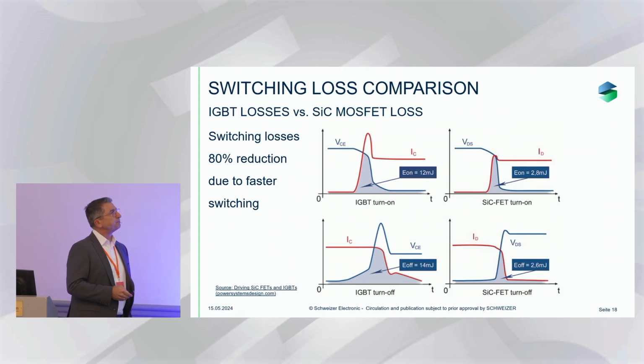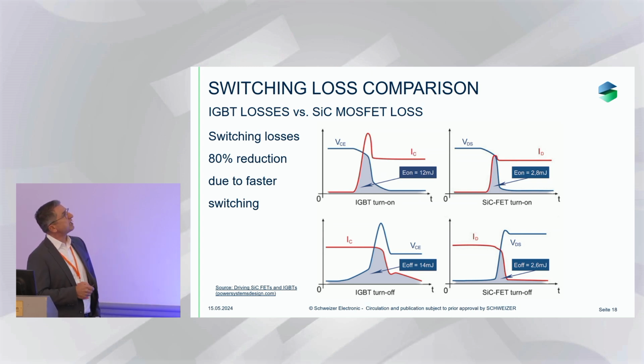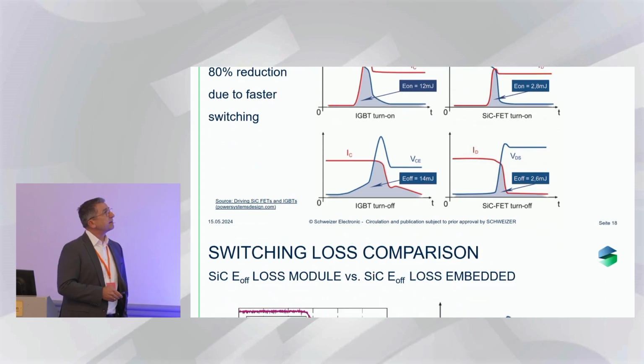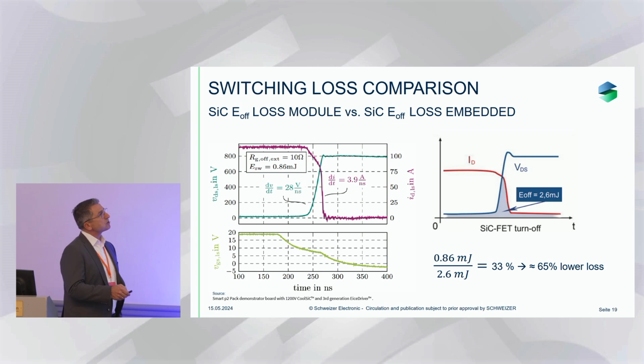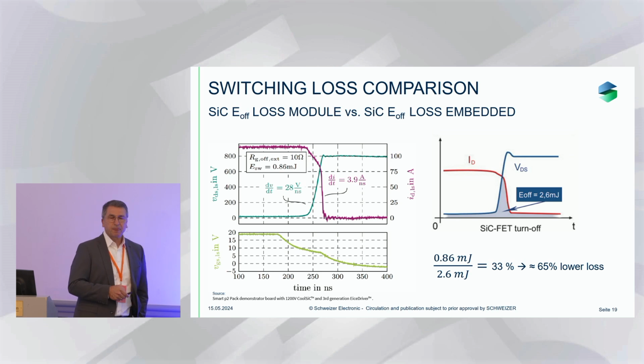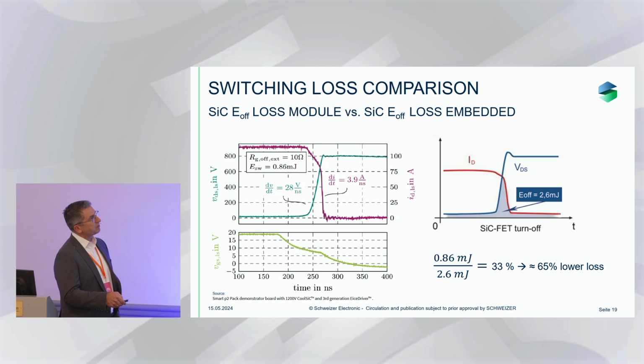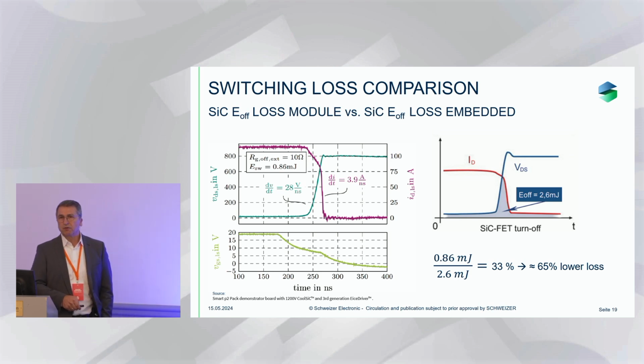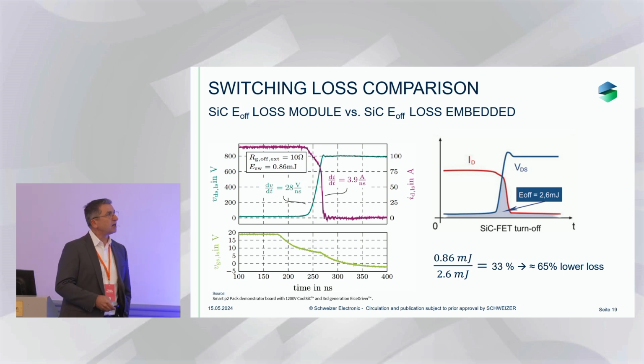So efficiency increase, where does it come from? First of all, everybody turns his back to the IGBT components because they're switching slow. And the first measure is to replace the IGBT components by silicon carbide, and you win the first 80% in switching losses. But what happens if you go to embedding with the silicon carbide components? Just keep in mind, in the module, you still create 2.6 millijoules per switching sequence. And we made the same measurements together with Infineon, and we found, even though the gate resistance was at 10 ohm, we switched not as fast as we could, with 28 volt per nanosecond. The switching loss was 0.86. So if you look at the equation here, you can see you can save approximately 65% of the switching losses compared to silicon carbide in a module.